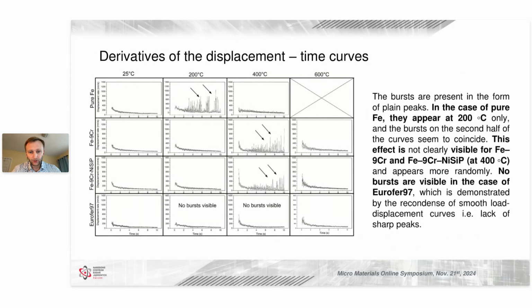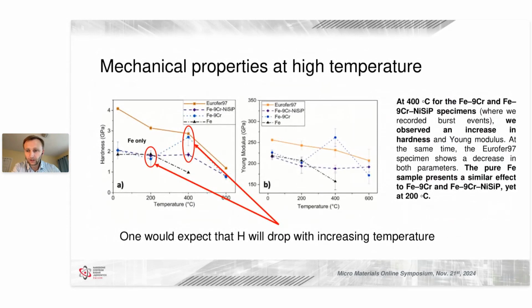In the next step, we plotted hardness and Young's modulus values as a function of temperature, and we saw that whenever the bursts appear, the hardness does not drop. Actually, it either remains at the same level in comparison to the previous temperature measurements, or even increases. And this is particularly visible for iron 9% chromium, where at 400 we saw a significant increase of the hardness value.